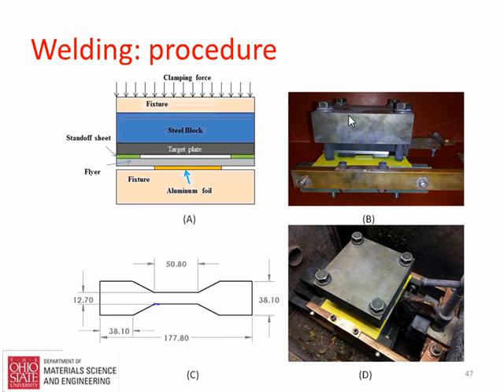So the actuator here is basically a foil in the form of a dog bone. We are still working on optimizing the shape of this, but the basic dog bone shape is to ensure that the current density in the narrowest region of this foil is the highest. We want the launch, or the activation of this foil, to happen there first because it has the highest current density.